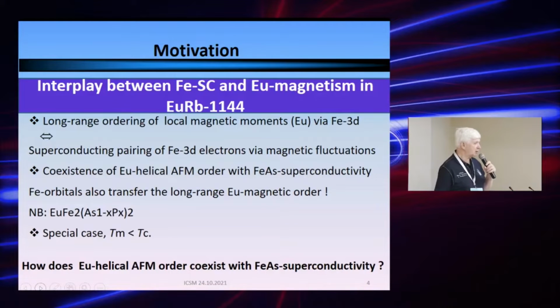At the same time, it is already established that the superconducting pairing of 3D itinerant iron electrons happens via magnetic fluctuation. So it is quite a complicated story. The magnetic ordering of the europium atoms, europium planes, appears to be not trivial. It's like a helix, and the planes are located quite far away from each other. So the mechanism of establishing the long-range order is not quite clear. It's discussed, and I don't think that it's clear, because the same iron orbitals participate, they form the Cooper pairing. At the same time, they should transfer the long-range magnetic order between the europium layers.